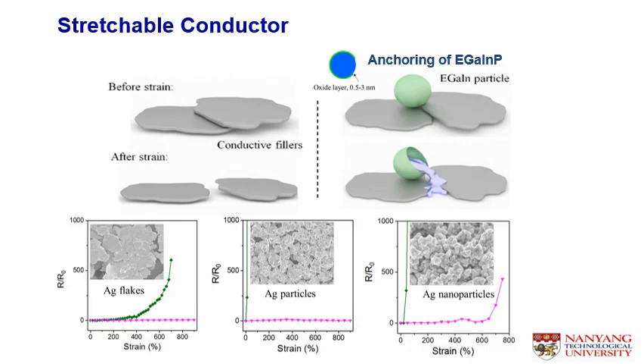In order to reduce the resistance increment as a function of cycling number, which is typically due to the separation of the metal fillers, we have introduced the presence of liquid metal in the form of nanoparticles. The nanoparticles has an encapsulated shell with a thin layer of 0.5 to 3 nanometer oxide shell, which can be broken upon stretching, releasing the liquid metal to connect between the metal fillers during stretching. Here, we can see that the addition of the liquid metal into the silver flake, silver particles, and silver nanoparticles has created a system that allows high stretching strain more than 600%.